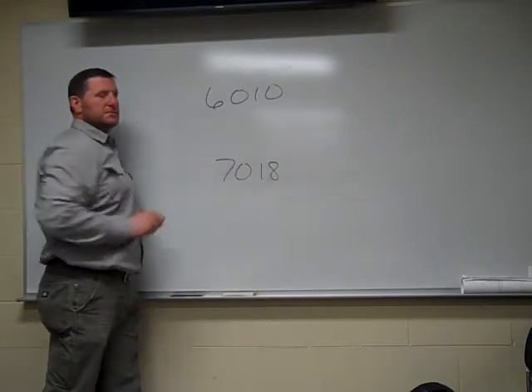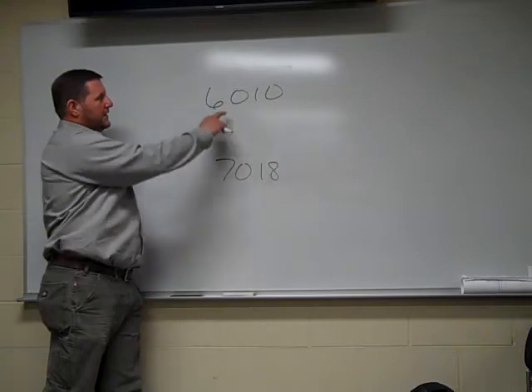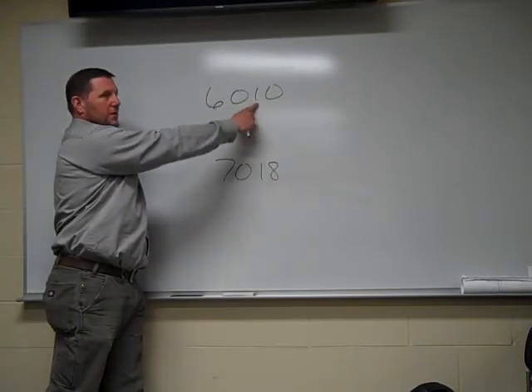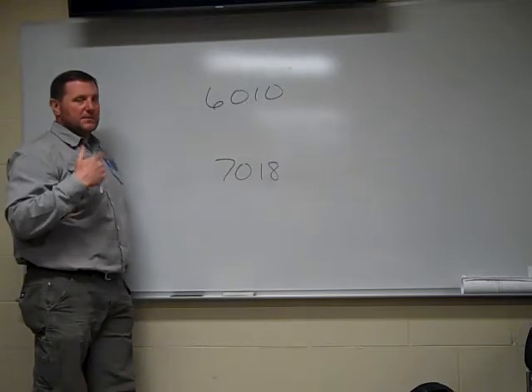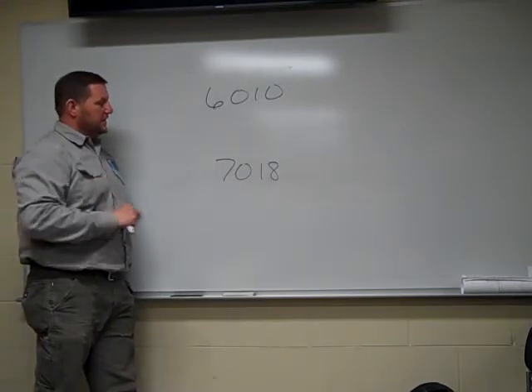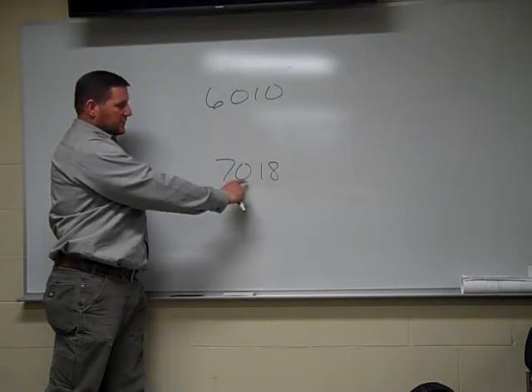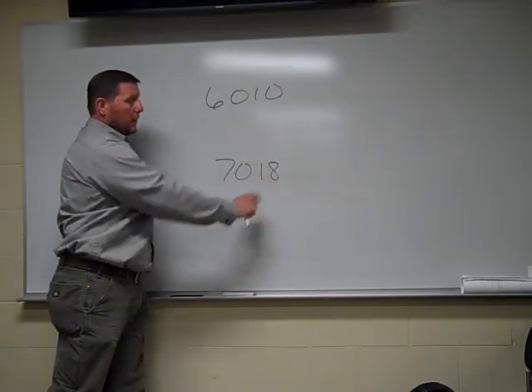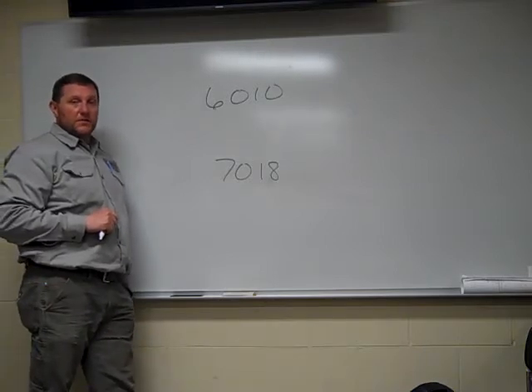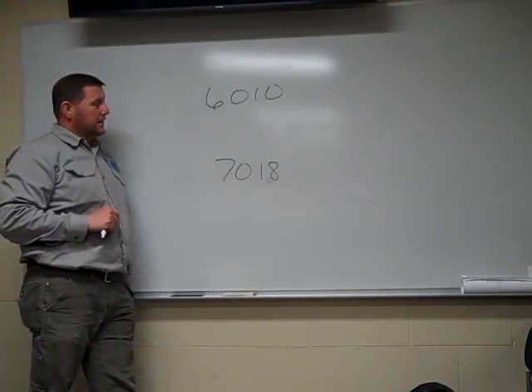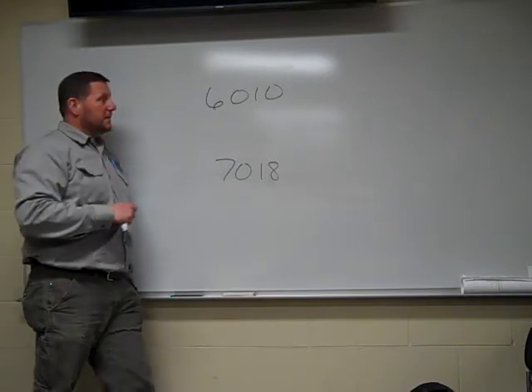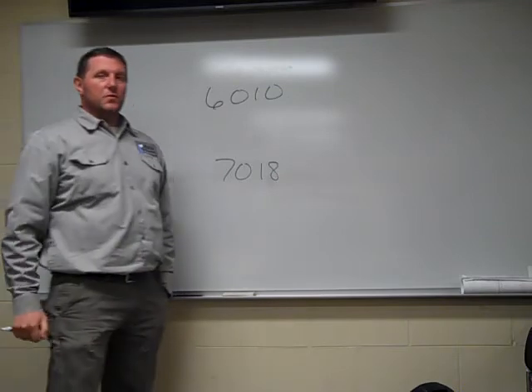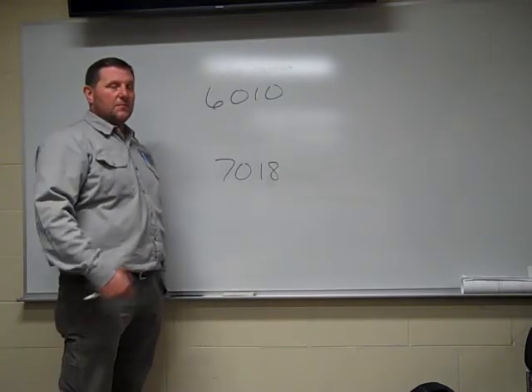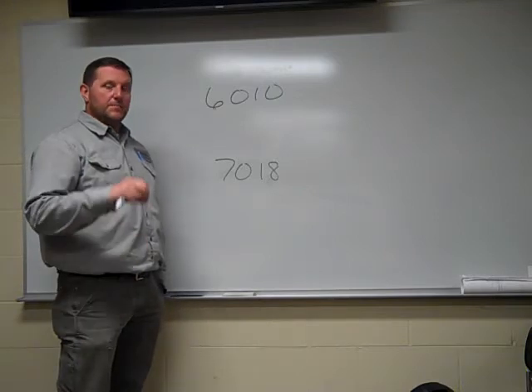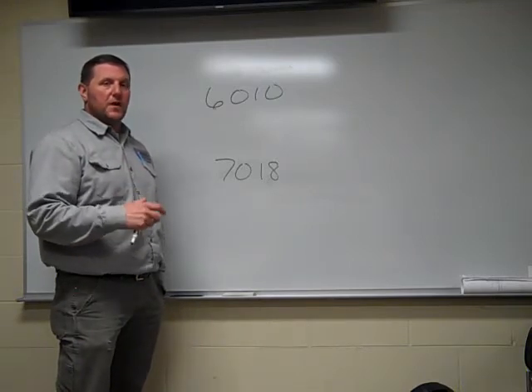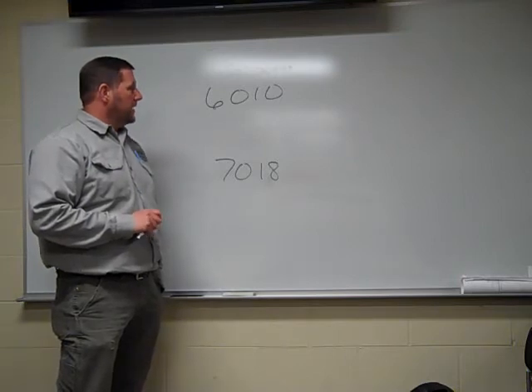6010, like I said, it's high cellulose. Run a DC electrode positive. 60,000 psi tensile strength, welded all positions, high cellulose rod, DC electrode positive for your current. 7018's got a 70,000 psi tensile strength, weld all positions, low hydrogen rod. Primarily you're going to weld it in DC electrode positive, and it's also stored at 150 degrees Fahrenheit. Now 6010s, they're typically not stored in a rod oven, because what actually happens is that they get too dry and the flux actually starts to crack off. So keep that in mind too.